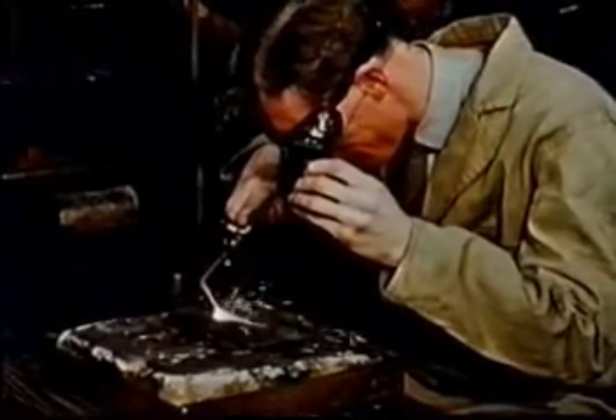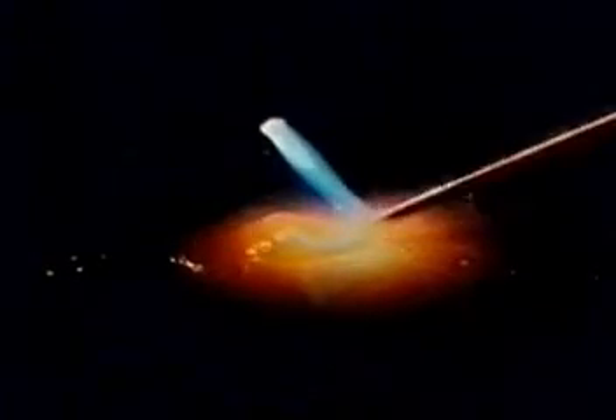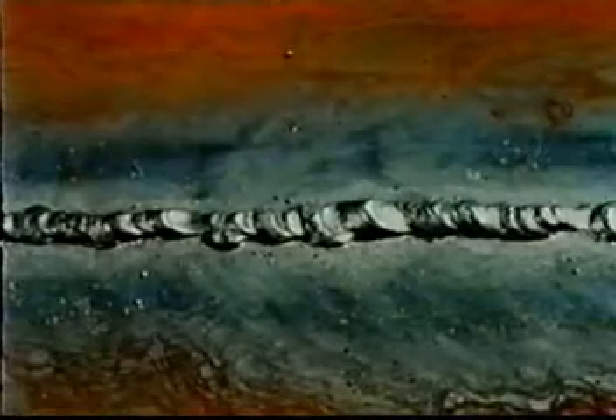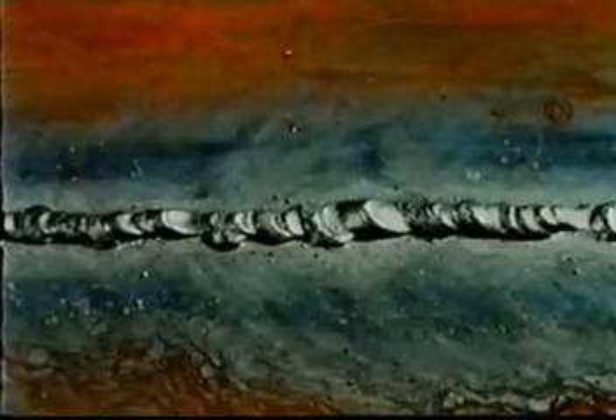Most of the basic mistakes are being made here. The blowpipe is shaking. Its movement is erratic, probably because it's being held too tightly. The flame is wrongly set and so not giving maximum heat. The rod and flame angles are wrong. The rod, instead of being fed into the pool, is dripping onto relatively cold plate and sticking. The nozzle is not in line with the line of weld, so there's a heavy build-up on one side and the operator is wandering off the straight line. The result is a cold, lumpy deposit with irregular ripples.